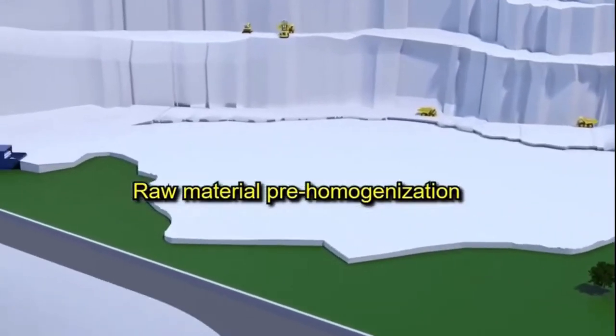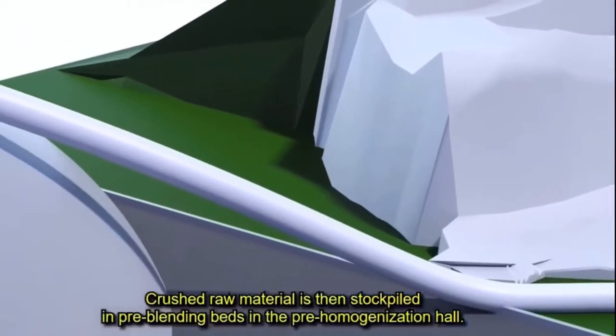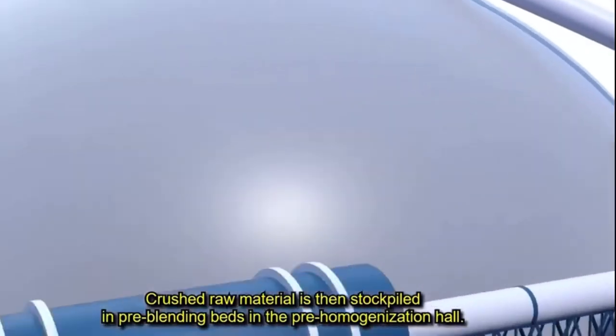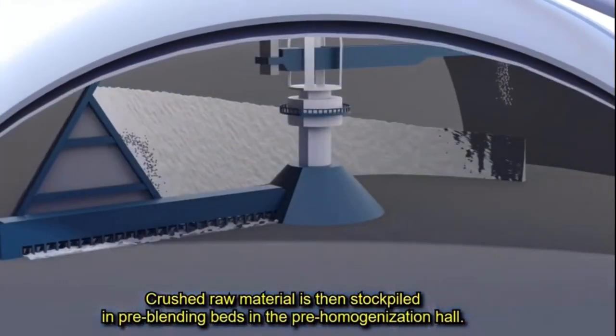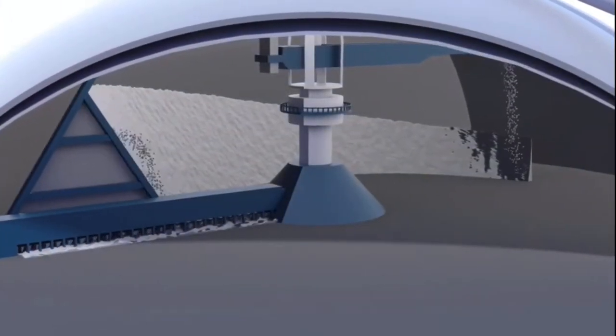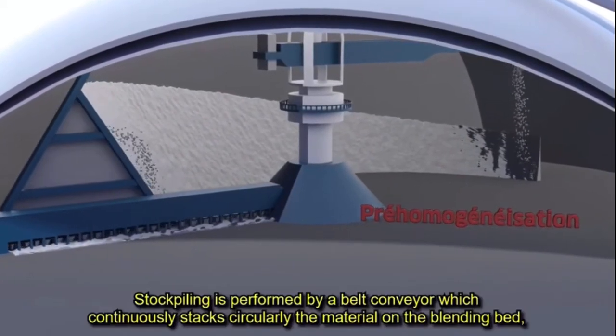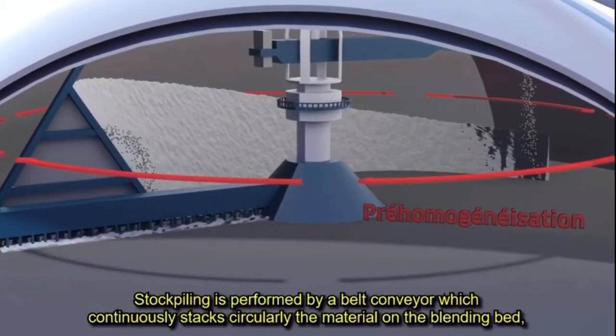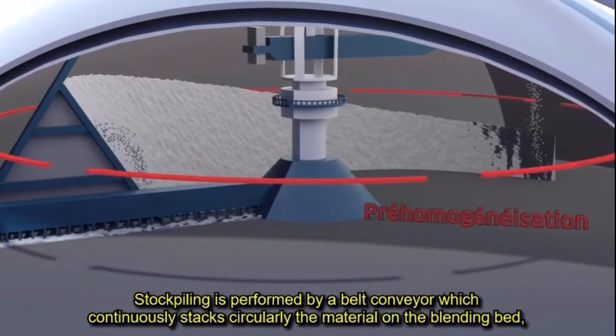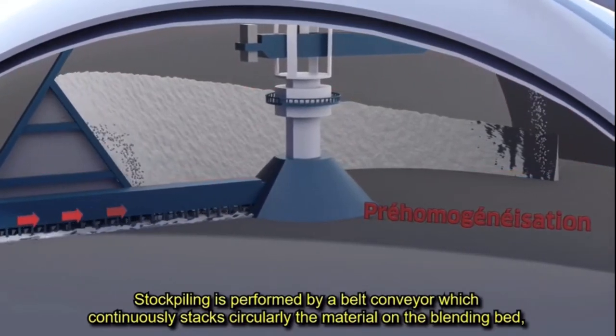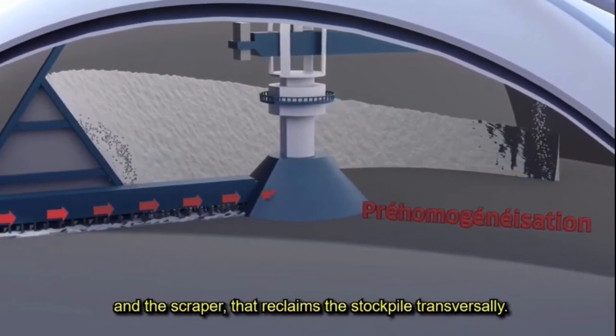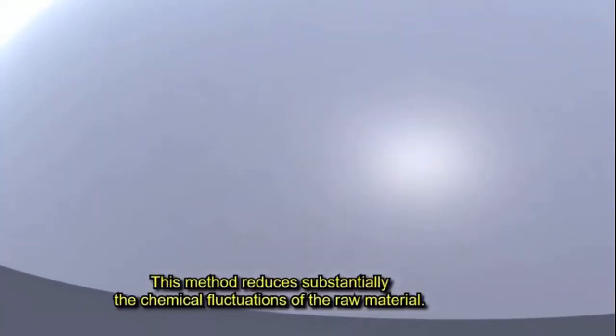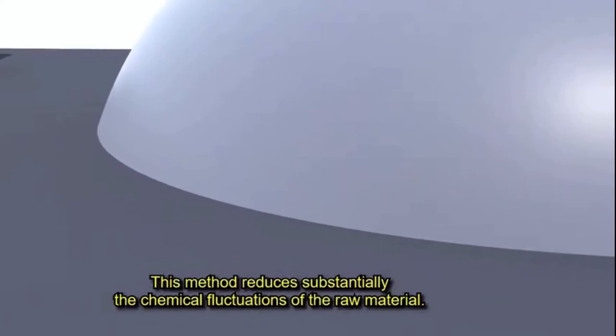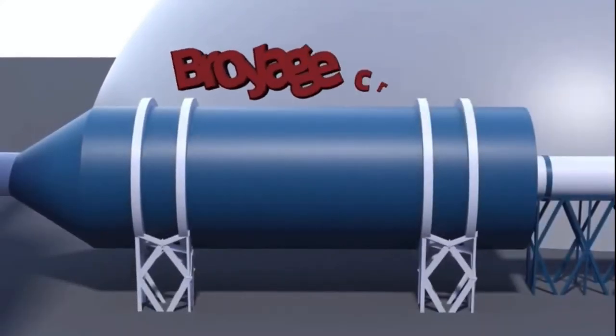Raw material pre-homogenization. Crushed raw material is then stockpiled in pre-blending beds in the pre-homogenization hall. The circular stockpiling is performed by a belt conveyor, which continuously stacks circularly the material on the blending bed, and a scraper that reclaims the stockpile transversely. This method substantially reduces the chemical fluctuation of the raw material.